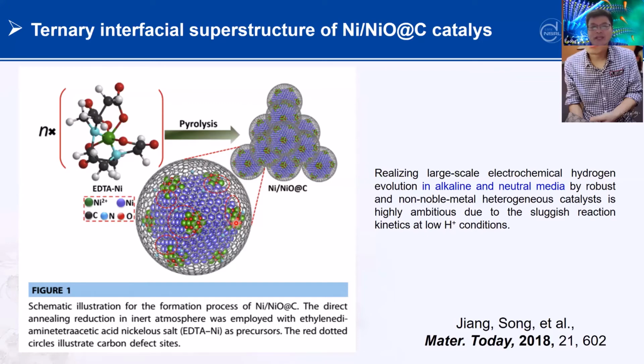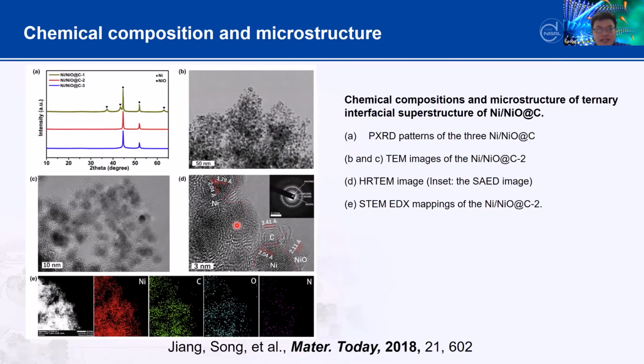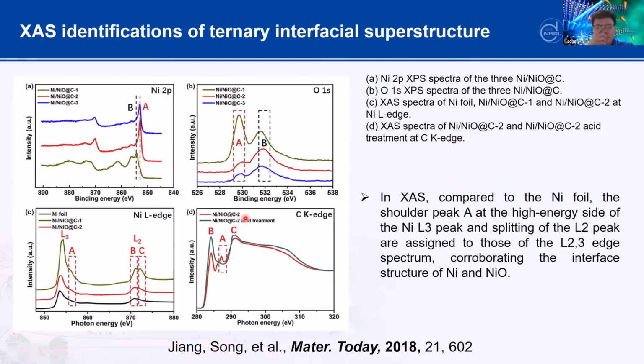By normal tools, you cannot really identify this structure. So in that case, we select the synchrotron radiation technique. As you can see by the TEM and XRD, this material is very unique, very tiny particles, with the metal inside and the carbon outside. Here you want to know how the carbon shell interfaces with the metal. Is there any chemical bonding, and how does this chemical bonding contribute to the properties? So we combine XPS with XAS to identify the interface and the superstructure.